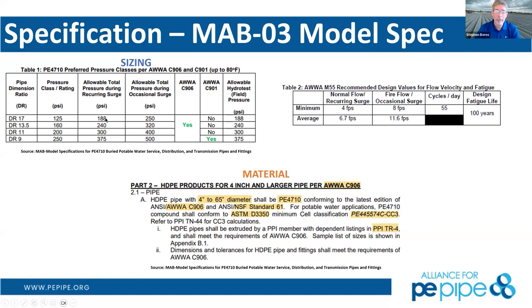So the thing about polyethylene, you have to remember, it has surge capacity because it's ductile on top of its pressure class. Not all materials have that. And pressure class means something different for every material. So just because you have a ductile iron with a certain pressure class, PVC with a certain pressure class, you don't match pressure classes when you design with polyethylene. You have to design it for its individual performance. So surge will be what causes the cyclic fatigue. Anytime you have a water hammer effect, let's say at 8 feet per second, you're going to have a surge or a fatigue event built into that.